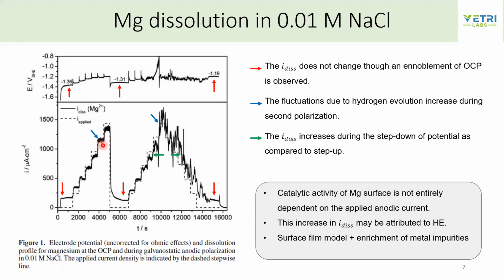But what can be seen from this data is the fluctuations, which actually represent hydrogen evolution. Initially the fluctuations were not that great, but then they increased during the second polarization, which again states that after this polarization, basically the surface changed - it was very different from what they had during the first polarization.